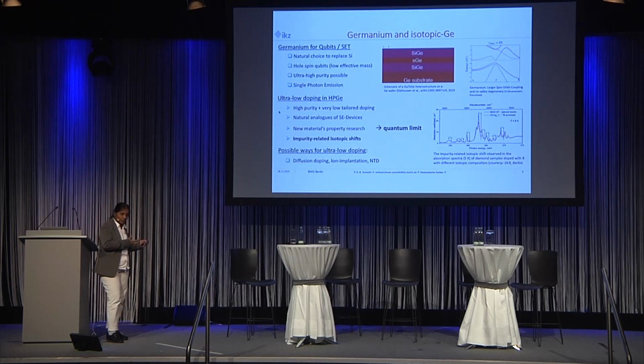For example, if you reach a very high purity in the order of a net charge carrier concentration of 10 to the 10, and you dope this material 2 orders higher, 10 to the 12, which is a very low doping, then you can put your impurity atoms in a place so that they can act as qubits, or you can manipulate them to make emission from these ions or atoms so that you can get single photon emission in these devices. There are a lot of possible ways to do this doping: you can diffuse the atoms, or do ion implantation, or neutron transmutation doping in isotopic materials. So these are the possible ways, and this way you can easily study the properties of the material for quantum applications.